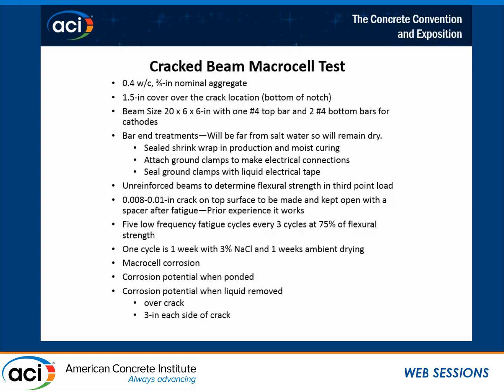There's no reason when you're testing corrosion in cracked concrete to go to a high water cement ratio and low cover. The crack is going to make things happen a little bit quicker for you. And they don't all go into corrosion at day one, so there is something about that. But you also used 1.5 inches of cover over the crack.